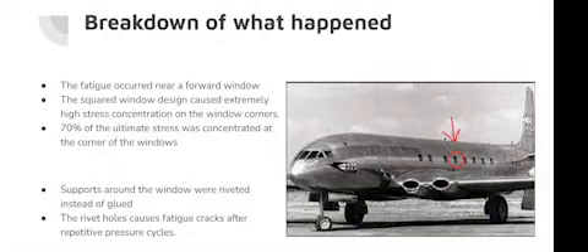There were many contributing factors that led to the failure of these planes. The first is that the squared window design caused extremely high stress concentration at the window's corners. Calculations revealed that up to 70% of the aircraft's ultimate stress under pressure was concentrated on the corners of the windows. A fatigue crack originated in a corner of one of the cabin windows. It advanced until the metal skin was punctured.